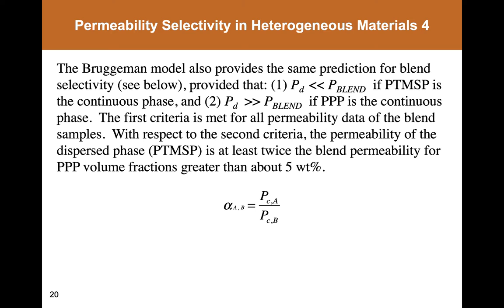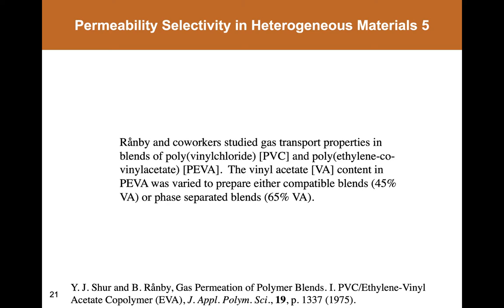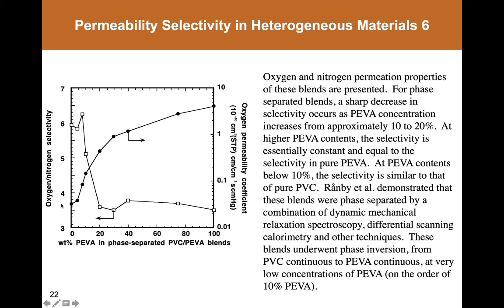Another example of this is shown in the work of Ronby and Schur, and they studied blends of polyvinyl chloride and polyethylene covinyl acetate. These blends are also phase separated, and they observed that as they increased the concentration of polyethylene vinyl acetate, or PEVA, in these blends, the permeability went up by a couple of orders of magnitude, and the selectivity underwent a dramatic step change at about 20 weight percent of the polyethylene vinyl acetate. They went on to study these blends by a variety of other techniques, as detailed on the right-hand side of the slide, and to show that even at low compositions of polyethylene vinyl acetate, one could have phase inversion in these blends.